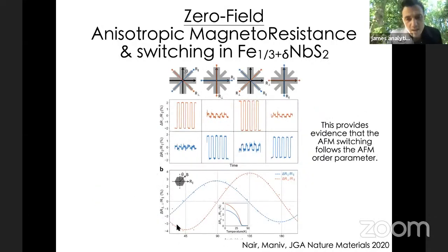What we found is that the angle dependence of what's called the anisotropic magnetoresistance matched perfectly with the angle dependence that we see in our applied electric field. So whether you pulse in the north-south or east-west direction and then rotate that around the sample, you get the same kind of angular dependence as you would if you applied a magnetic field and rotated that around the sample. In other words, the electric field and the magnetic field must be having the same kind of effect on rotating the average Néel vector by shifting those domain boundaries.